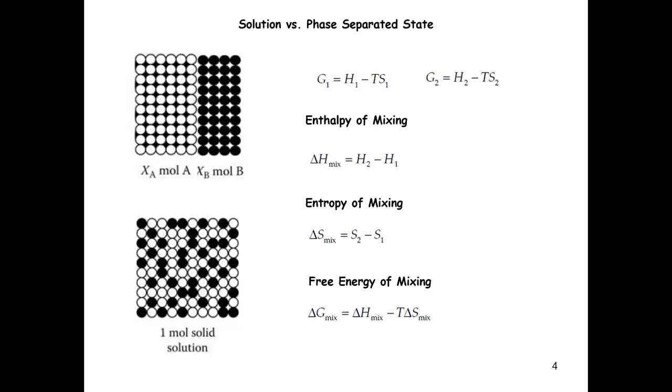Yeah. Okay. In that system, are we ever going to see a phase transformation at any finite temperature? In the system where the enthalpy of mixing is smaller than 0, are we ever going to see a phase transformation? No, right? Why is that? Because we know the entropy of mixing always favors the mixing state, because by mixing you can always increase this guy. And we have a negative sign here, so this contribution can always be negative. So it favors mixing, right?